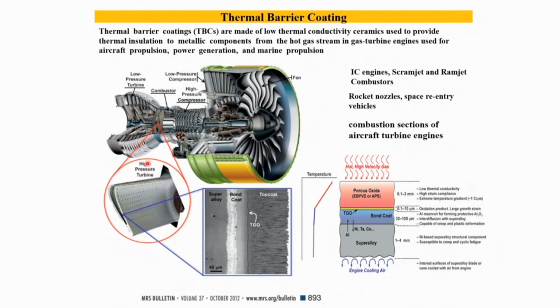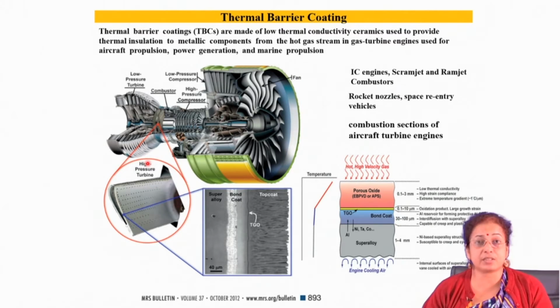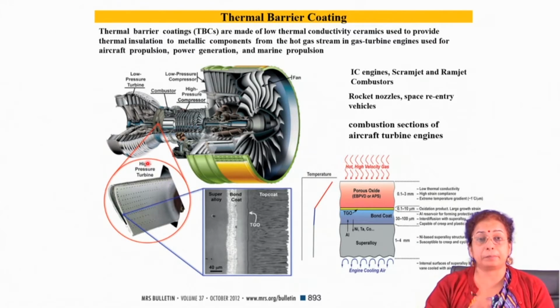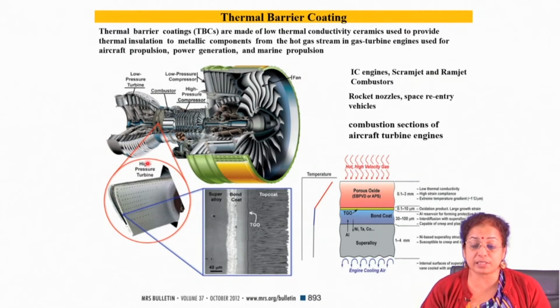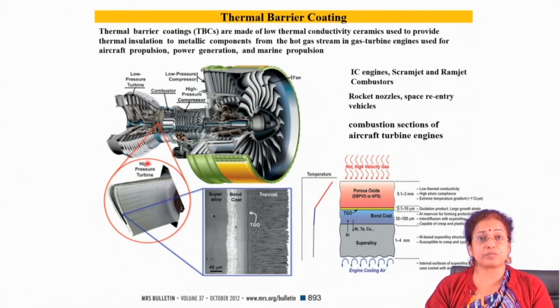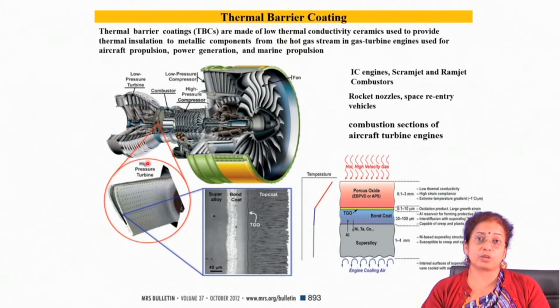As I mentioned, thermal barrier coating is a kind of oxide based coating which, when applied onto the surface of the substrate, offers high temperature oxidation resistance significantly. But the thermal barrier coating itself does not offer oxidation resistance property; it acts as an insulating barrier on the surface of the substrate. So, the actual temperature experienced by the substrate is reduced to a great level. For example, by the application of yttria stabilized zirconia thermal barrier coating, the temperature experienced by the nickel based or iron based super alloy can be reduced by 50 to 100 degrees Celsius. This reduction in temperature is very helpful, because naturally the overall oxidation resistance and service life of the component increase to a large extent.